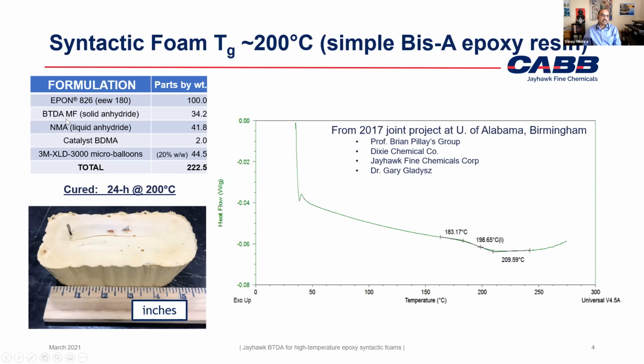And the idea was that the BTDA can give you a very high temperature behavior, high TG and so forth, but the liquid NMA anhydride will act as a reactive diluent and improve the processing properties for the syntactic foam formulation. So this system, of course, Rob, you'll recognize one of your products here.